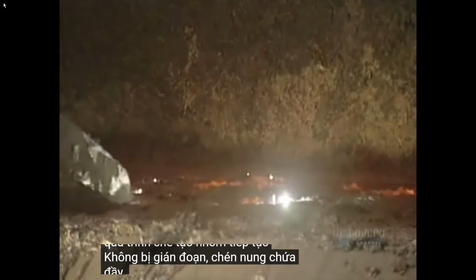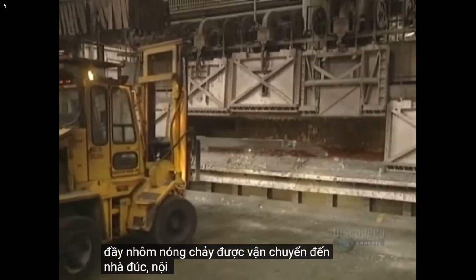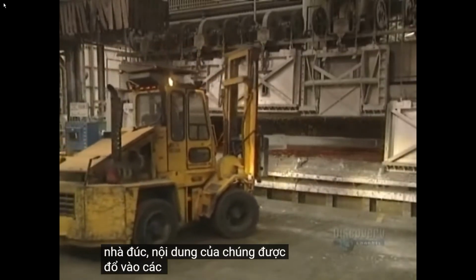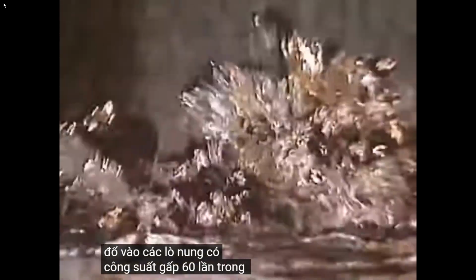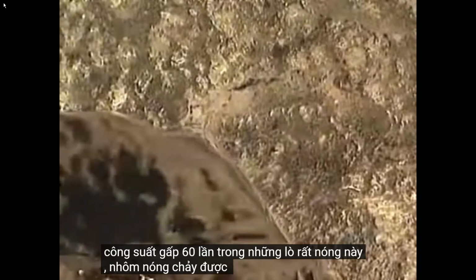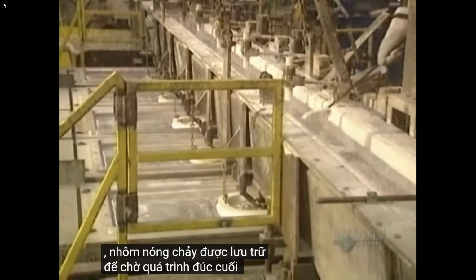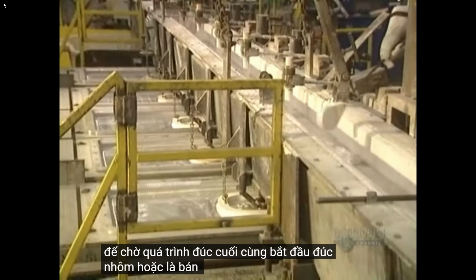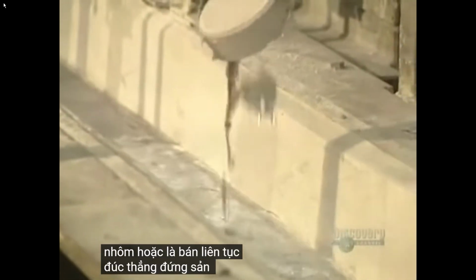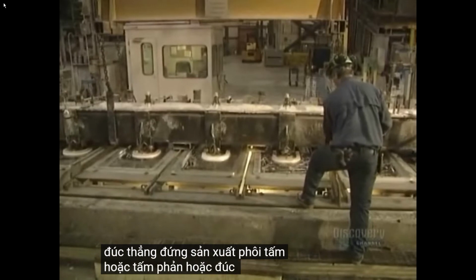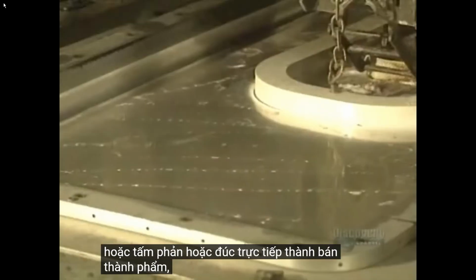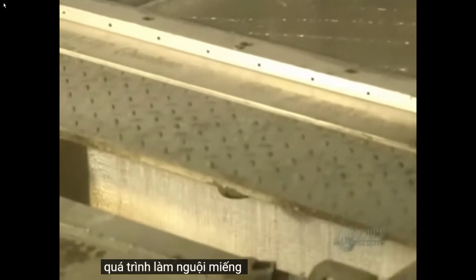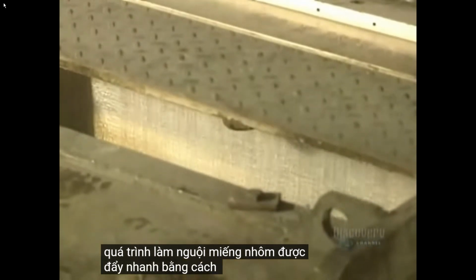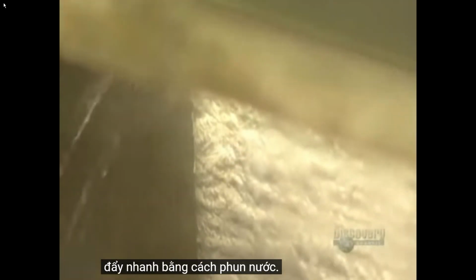The crucibles filled with molten aluminum are transported to the casting house. Their contents are poured into holding furnaces which have a capacity of 60 tons. In these very hot furnaces, the molten aluminum is stored to await casting. Finally, casting begins. The aluminum is either semi-continuously vertically cast, producing ingots, sheets, or billets, or directly cast into semi-finished products. The cooling of aluminum pieces is accelerated by water sprays. The large rectangular ingots, which can weigh up to 25 tons, will head for hot rolling.